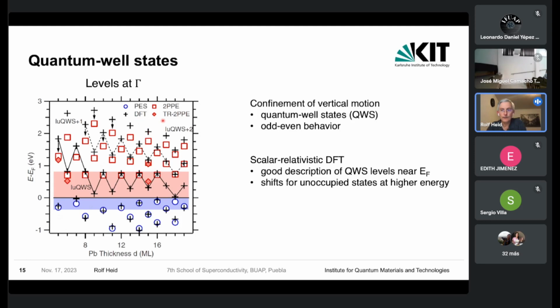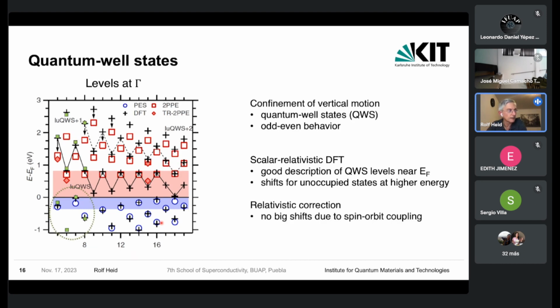Interestingly, density functional theory can very nicely catch this trend. The density functional theory calculations are put here on top of this experimental data as these crosses, and you see very nice agreement, at least in this area closer to the Fermi level. Now, these calculations have been done without spin-orbit coupling, so we were worried that spin-orbit interaction might change this good agreement, but calculations including spin-orbit interaction do not really shift these electronic energies much, and so we still have a similar, good agreement.